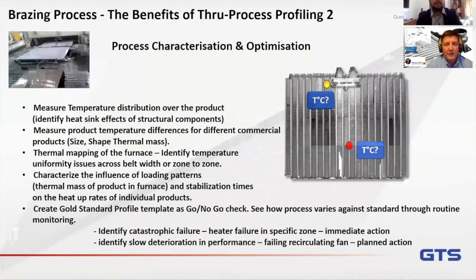Okay, Victor. So obviously, if we're able to measure the product temperature through the furnace, when we're talking about uniformity, we're talking in this particular case not about the uniformity of the furnace, though we can use the same technology. We're talking about uniformity of heating at the product level. So by selective placement of the thermocouples across the product itself, you can measure whether there's any temperature imbalance across that product.